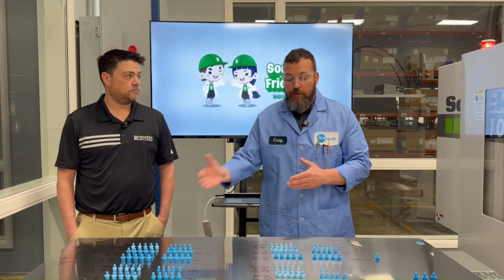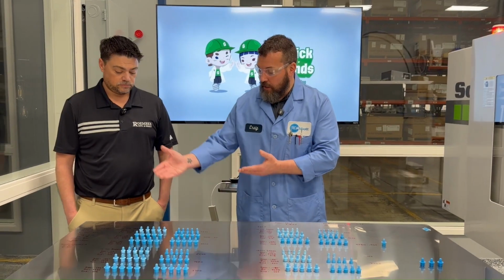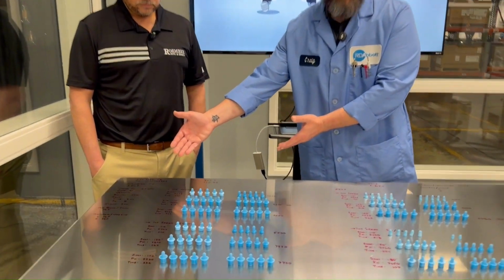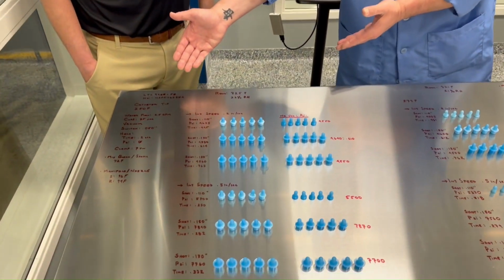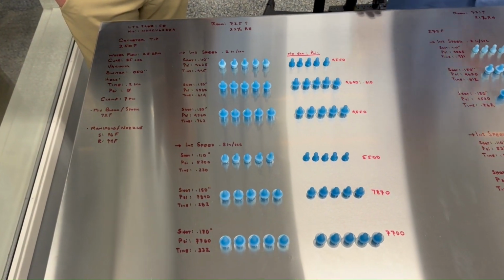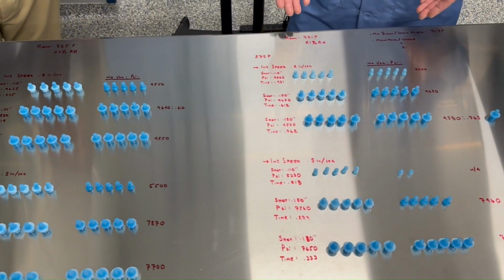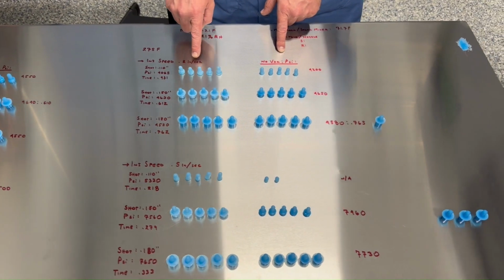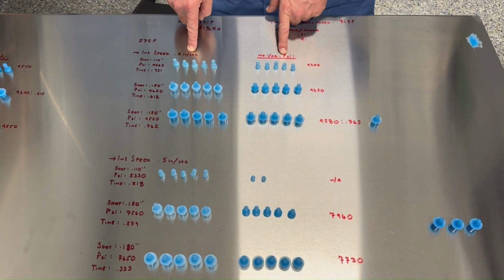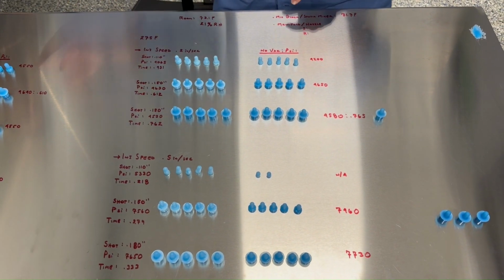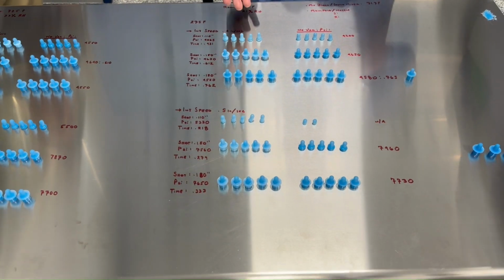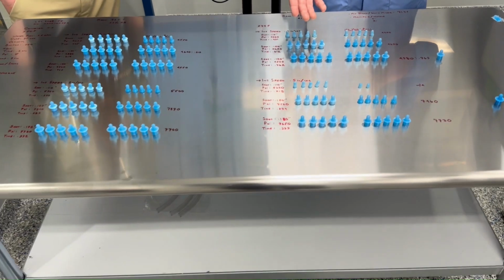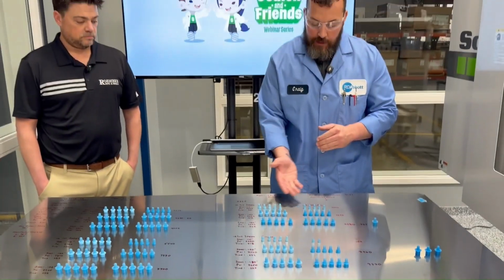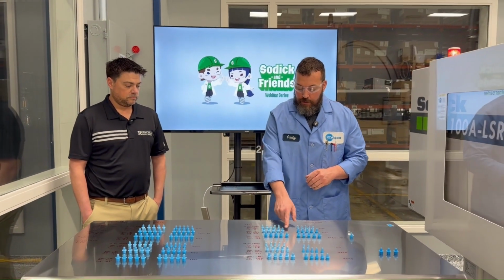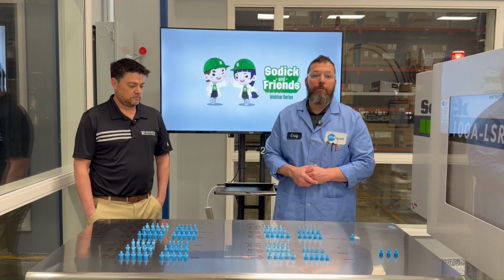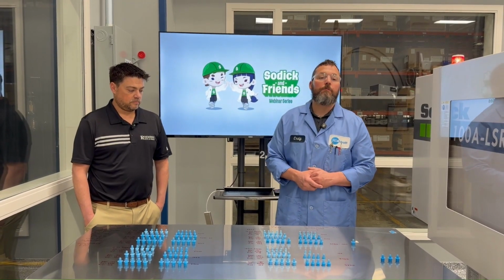And you know, a few differences here, as we can see, I started at 250 degrees Fahrenheit, utilizing the low temperature cure material, and then I moved up to 275. But my two categories, I have vacuum, and then I'm pulling no vacuum. So as we go through increasing just shot size, no holding pressure, we can see the difference in fill, but also the amount of air that we're pulling through that material as we're filling out.